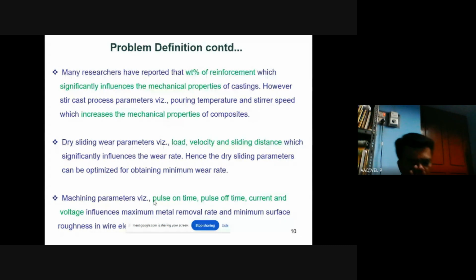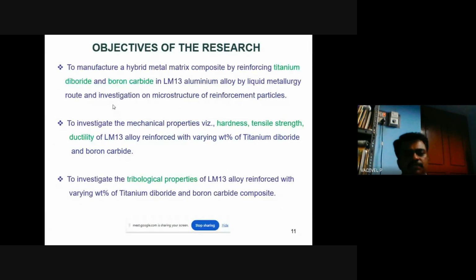When coming to the wear properties, dry sliding wear parameters like load, velocity, and sliding distance influence the wear rate of the material. Hence we have chosen the dry sliding parameters, and they are optimized for obtaining the minimum wear rate. And when coming to the machining parameters in the wire EDM: pulse on time, pulse off time, current, and voltage. These four parameters influence the maximum metal removal rate and minimum surface roughness in the wire electric discharge machining process.